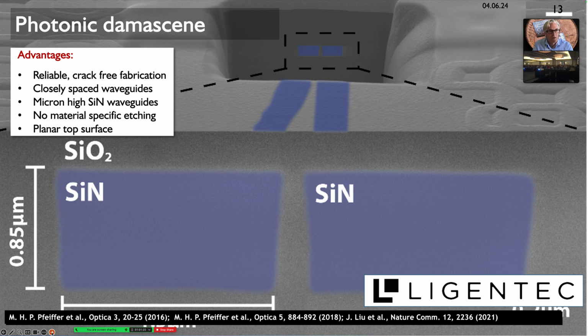Also very closely spaced waveguides. You don't suffer from the problem of gap filling, and it has brought down the losses by now about a factor of 100 compared to what was possible a decade ago.